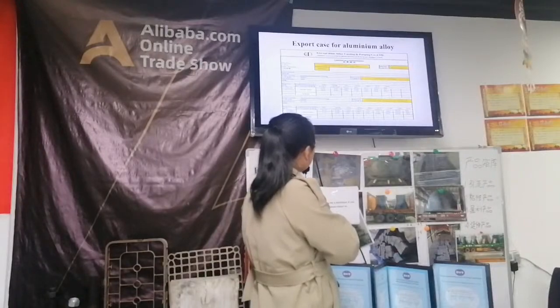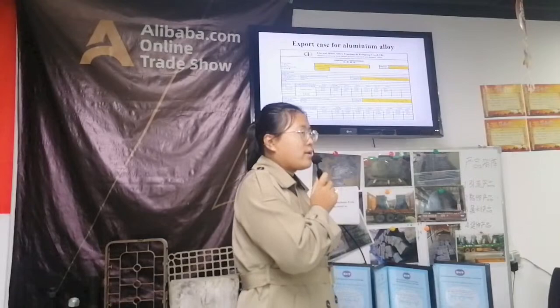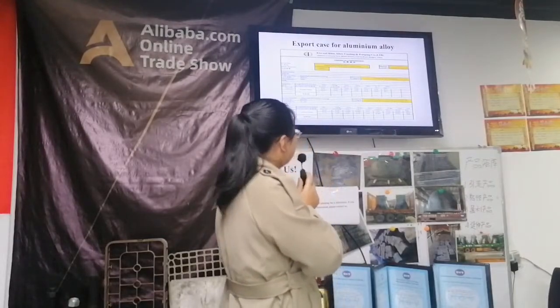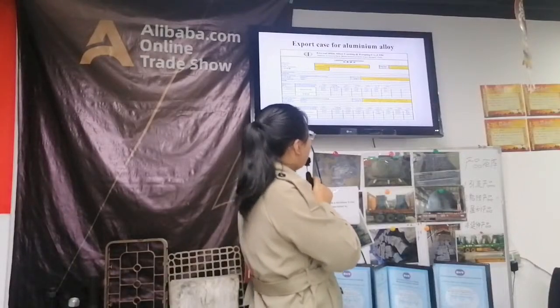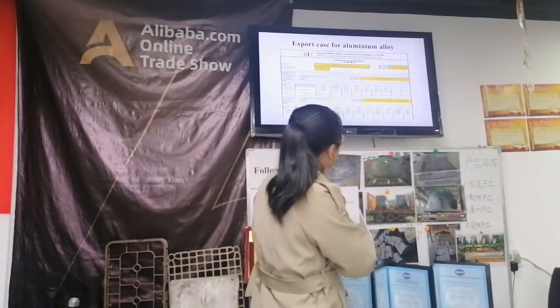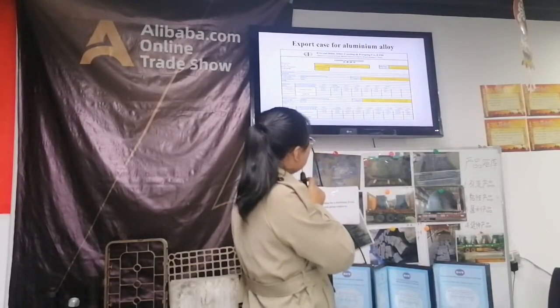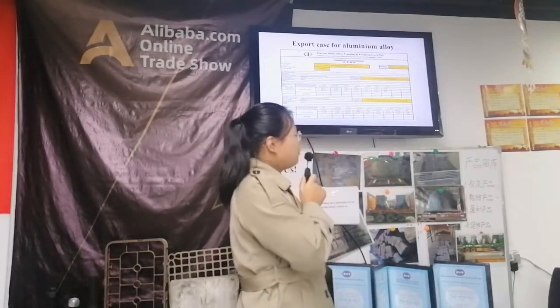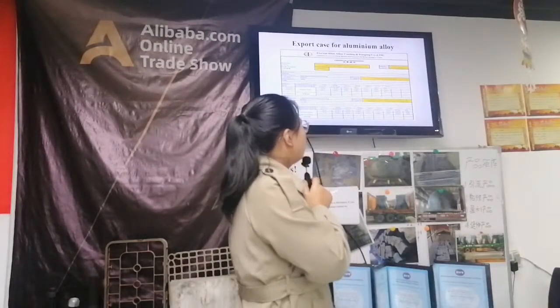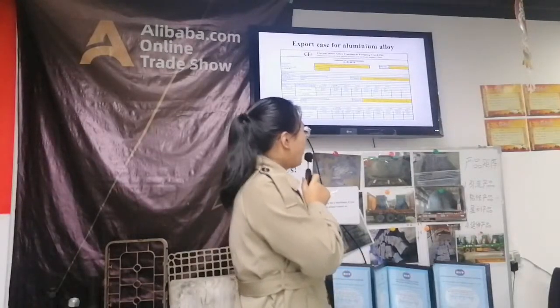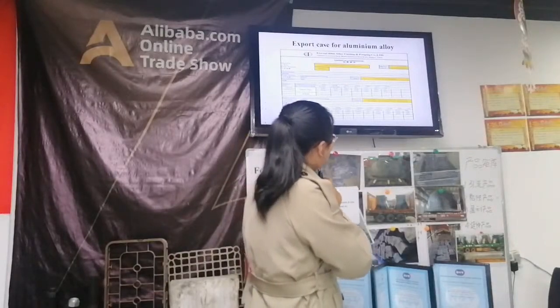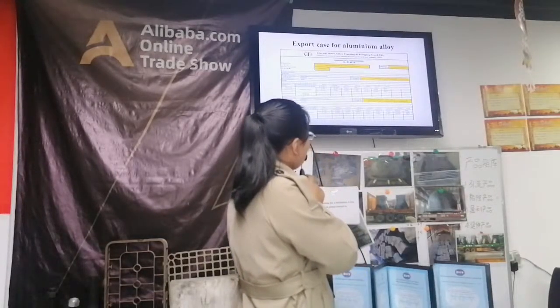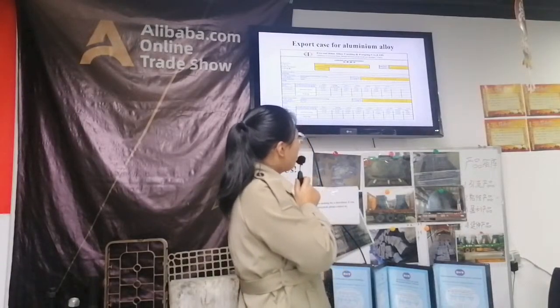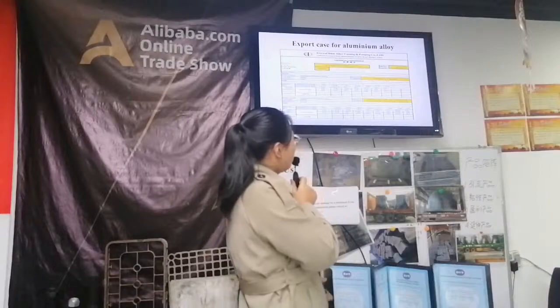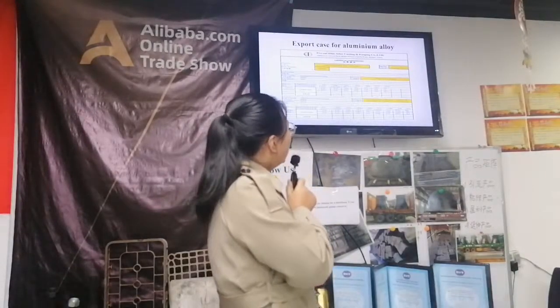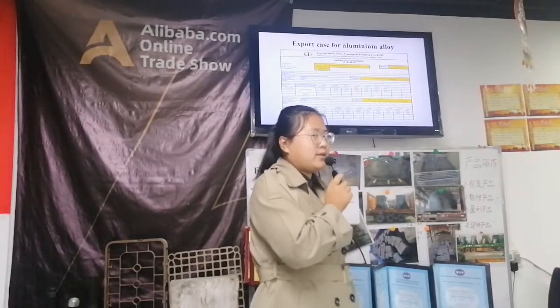Next, chemical composition is ZL101. For composition, silicon, the range is 6.5 to 7.5%, actual value 6.9. Magnesium, the range is 0.25 to 0.45%, actual value 0.42. And the aluminum is balanced.